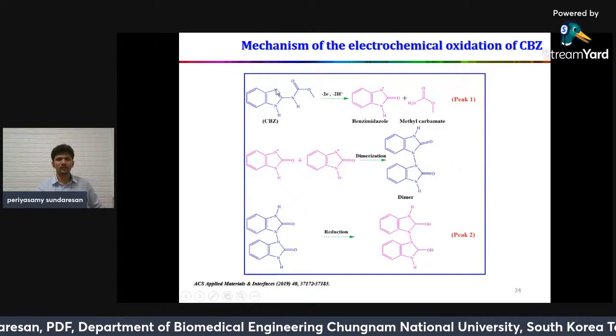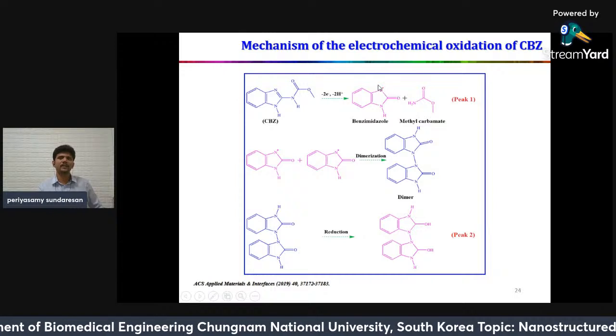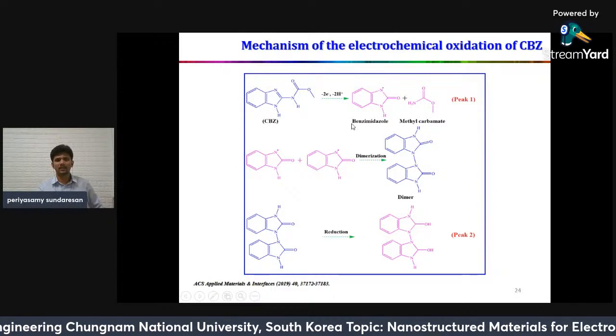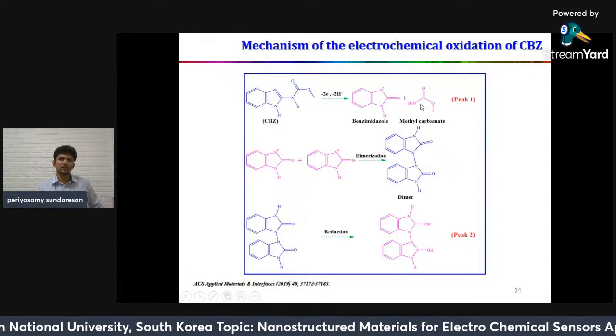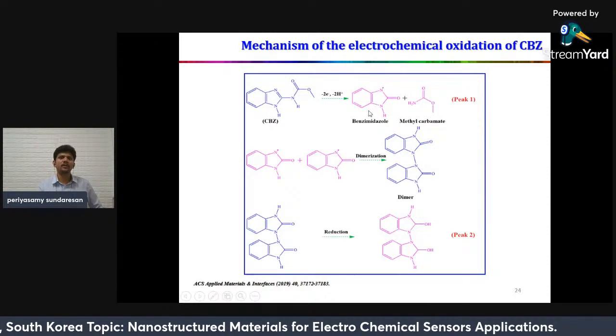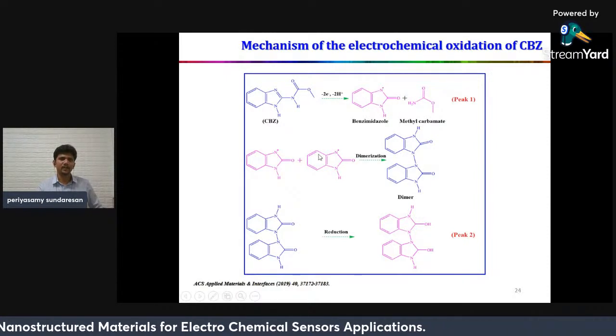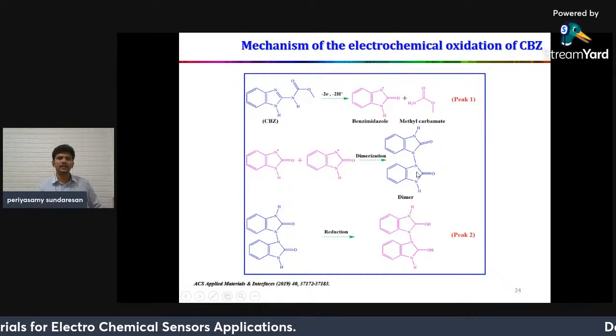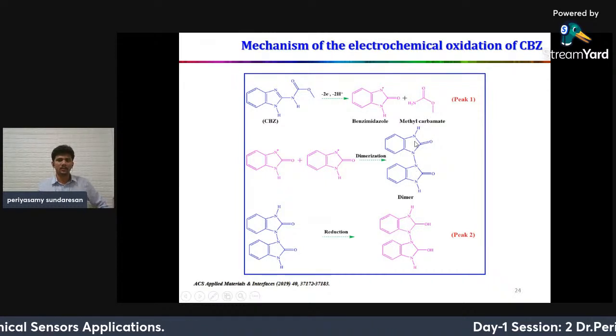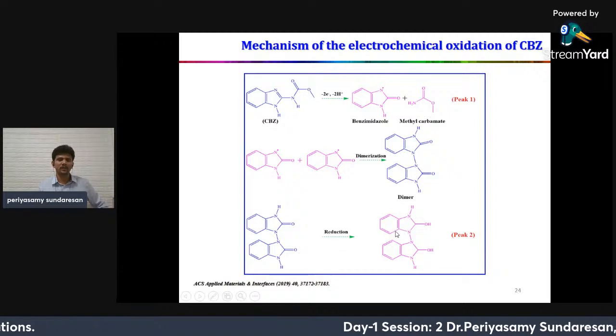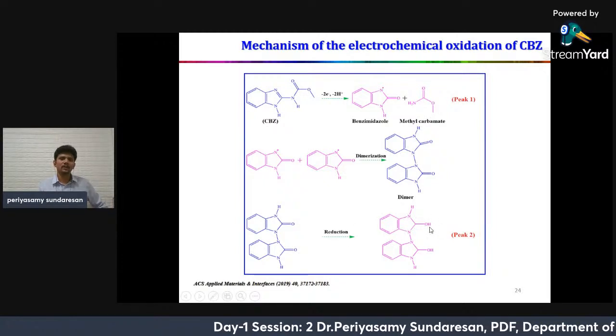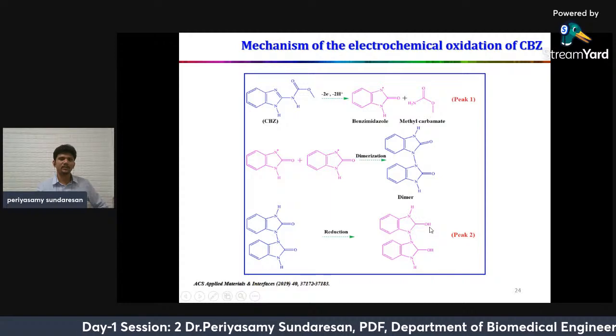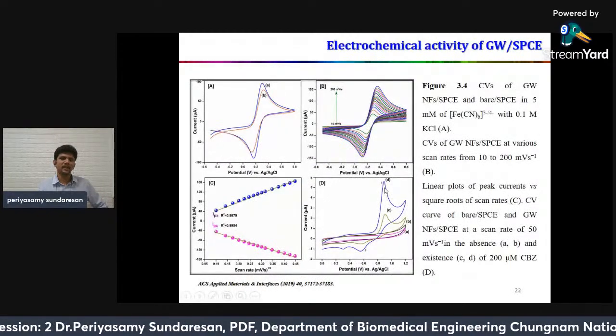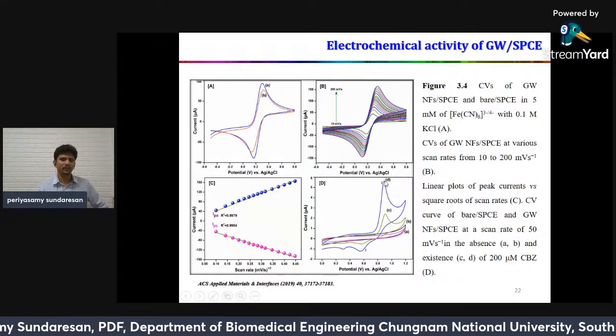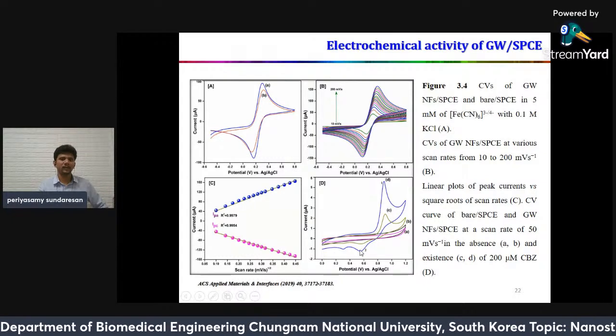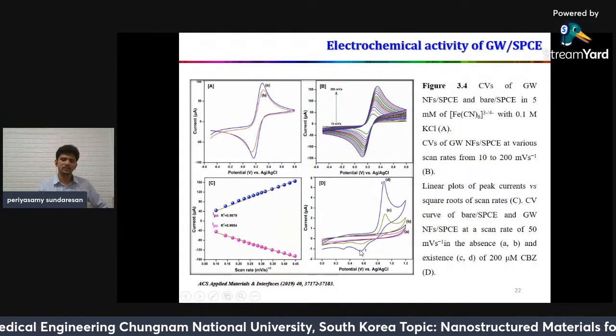Initially the nitrogen groups go to the oxidation state. It gives a nitrogen radical like a benzimidazole radical. Then the unstable intermediate benzimidazole radical combines with two groups, then dimerization occurs. The dimer is reduced to form an alcoholic group. This gives a reduction peak. So this is the major oxidation peak of benzimidazole. This is the final dimerization reduction peak.